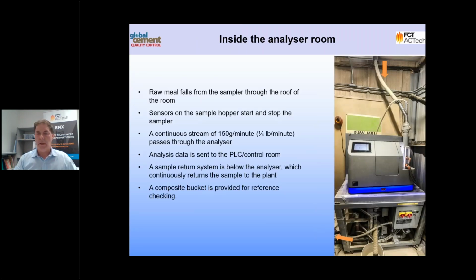So this is the XRF raw meal analyzer mounted on its automatic sample return system. This is the return system at the bottom here, obviously the analyzer at the top. So the raw meal drops down from above into the analyzer, where it is mixed and prepared continuously for the sample presentation system. So as I said, about half a cup of material passes through the unit each minute, and after it's gone through the analyzer, it drops out and then it's pneumatically conveyed back into the process. Also down the bottom here, we've got a bucket, and that's used to take a composite sample, which is used for the laboratory.